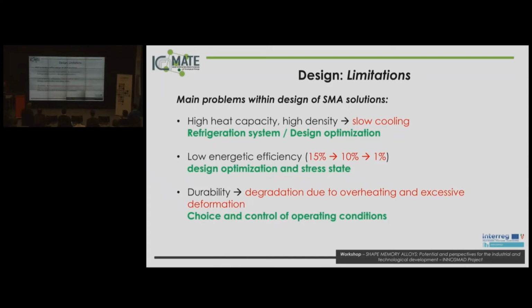The main limitations in the design with shape memory alloys are the high heat capacity together with the high density of these alloys, which give the problem of the slow cooling phase when we are dealing with, for example, actuators, because actuators need to be continuously activated, and the transition always has to be activated and then done again. And so if these shape memory alloys have this high heat capacity and high density, the cooling phase is quite slow, and this is not a very good point for the applications. And so the solution is to optimize the design of the component, and maybe also to design a refrigeration system to help the material for the cooling.